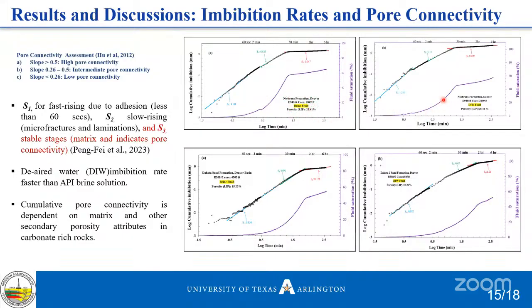Another thing to point out here is that this and this are the same sample, but with different time to reach the top and a different rate of fluid saturation. The significant difference is the fluid type. This is brine, which is salt water that we prepared in the lab, and this is the distilled water, which we call a DI fluid. You can see that the porosities are the same.